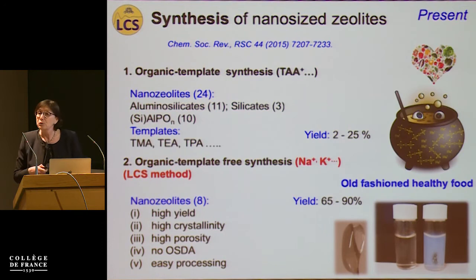Therefore, during the last 10 years, we focused our attention on the so-called old-fashioned healthy food, which means we try completely or partially to replace these organic templates with inorganic cations such as sodium, potassium, lithium, cesium, etc. Currently, we could synthesize 8 nano-zeolites with a high crystalline yield in the range of 65 to 90%, which is comparable to commercial production of zeolite. And also these materials have high crystallinity, high porosity, and no organic structure-directing agent was applied at all.